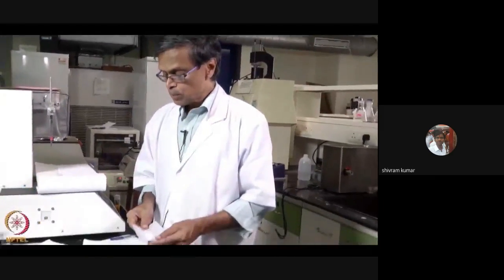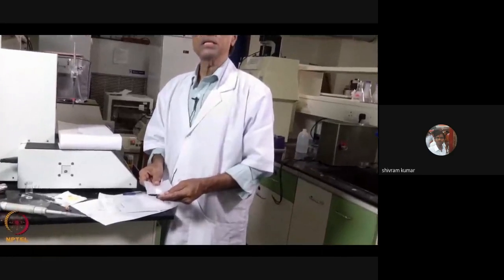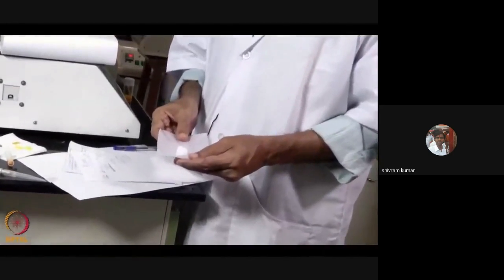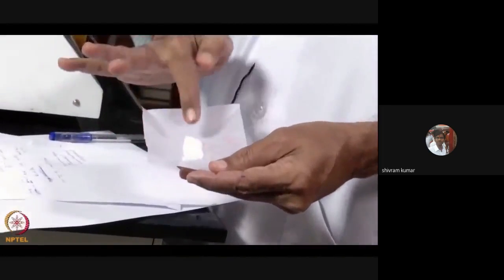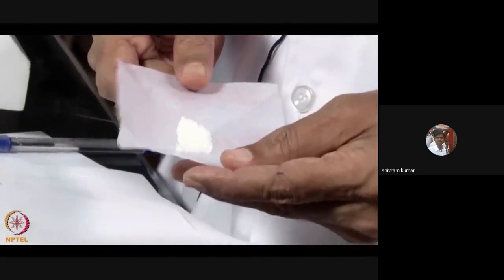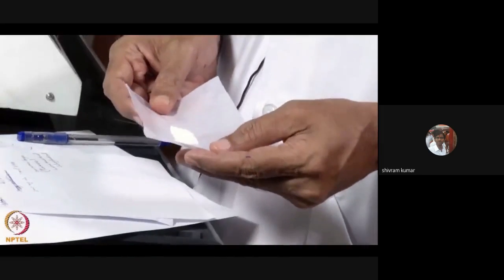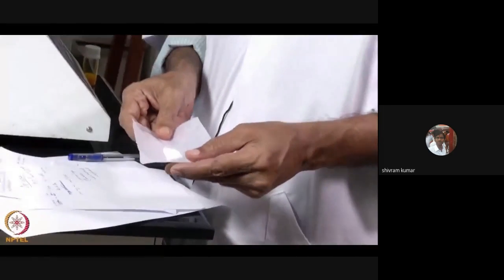We can't directly coat curcumin onto the polymer, so we use polyvinyl alcohol. This is an FDA approved polymer of molecular weight 140 kilodalton. We have to prepare a PVA solution in water. So we take 500 milligrams of PVA in 2 ml water. We heat it to 70 degrees centigrade in a water bath for 15 minutes so that the PVA completely dissolves.